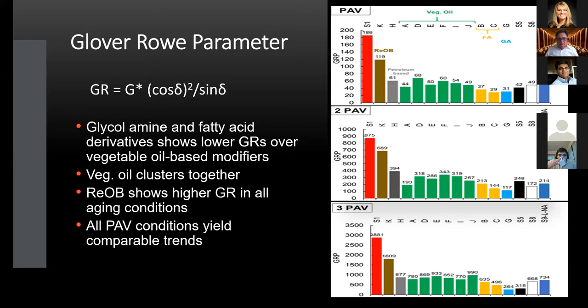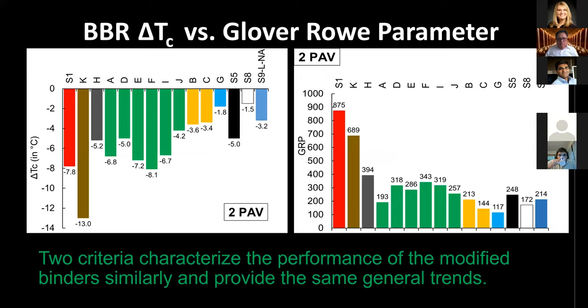The glycolamine and fatty acid derivatives show lower general Glover-Rowe values than vegetable oil-based modifiers. Those vegetable oils cluster all together; typically on all of the rheological properties, we saw a very consistent trend with all of the different vegetable oil-based modifiers. The REOB shows the highest Glover-Rowe in all aging conditions. And again, those PAV conditions yield comparable trends, as you can see by the graphics.